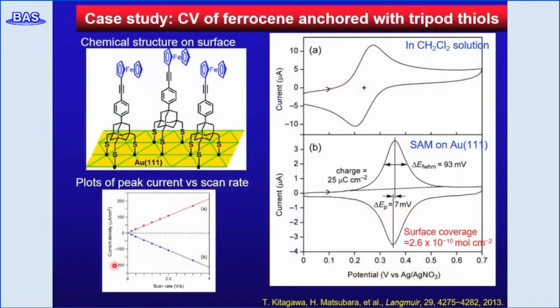Now I'd like to present some papers on molecular self-assembled films as examples. The first is the electrochemical study of a ferrocene SAM film with a tripod thiol anchor immobilized on a gold 111 surface. Here, reversible waves are seen at 0.24 volt in dichloromethane solution.